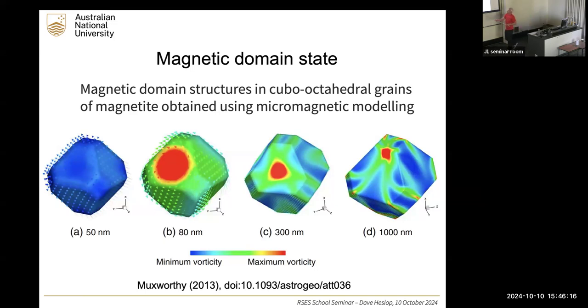So what we can see at 50 nanometers, all our little arrows are basically pointing in the same direction. This thing is what we call uniformly magnetized. Okay? All these elementary dipoles are pointing the same way. Get up to 80 nanometers, and suddenly you can see the arrows here are corkscrewing around, forming what we refer to as a vortex of spins that goes through the crystal. It's doing this in order to minimize its overall energy.